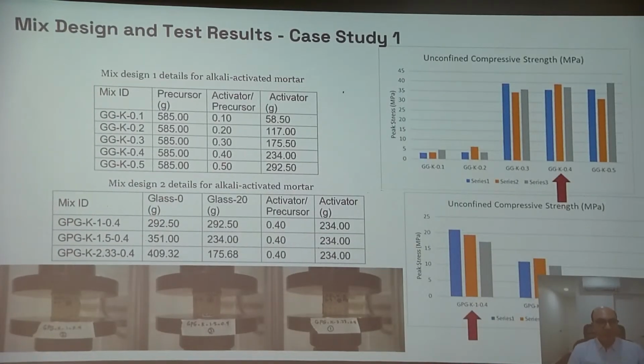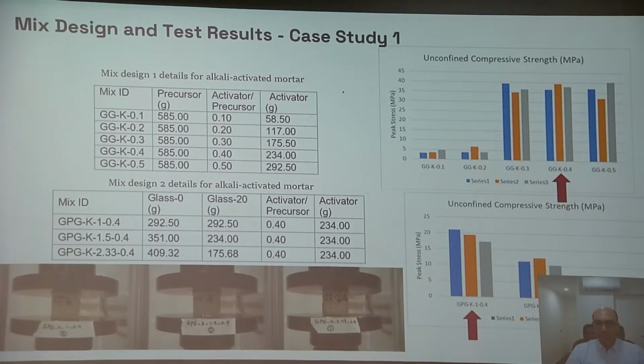To stabilize this soil, we first designed an alkali activated mortar using waste glass by including different percentages of activator to precursor and testing them through mechanical test of UCS properties. So the unconfined compressive strengths of different mixes after curing were examined, and we selected the optimum one, which was 0.4 activator to precursor content.